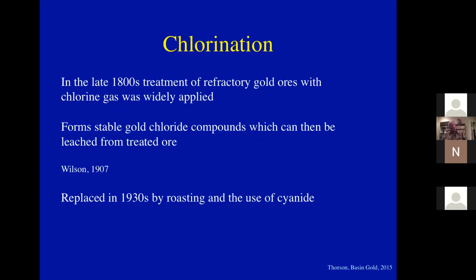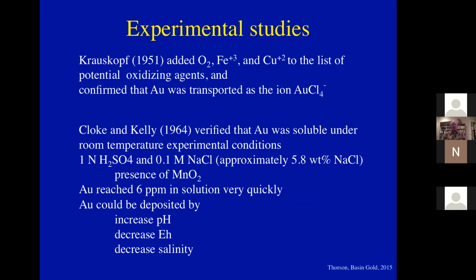Now, some of that work had already been put to use in the 1800s, where refractory ores were treated with chlorine gas, which formed stable gold chloride compounds, which were then leached from the treated ore. Now, that was abandoned in the 1930s when cyanide turned out to be a much safer way of treating refractory gold ores. And that's been largely abandoned, but the solubility of gold in chlorine-rich solutions has been worked on for a long time.